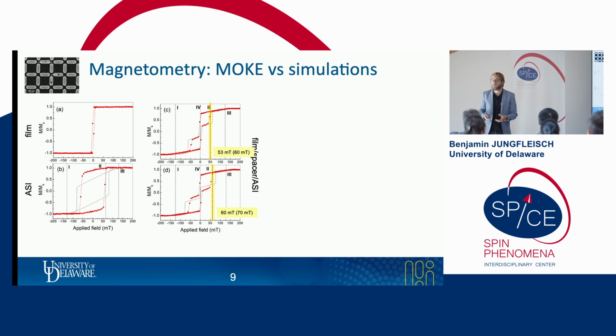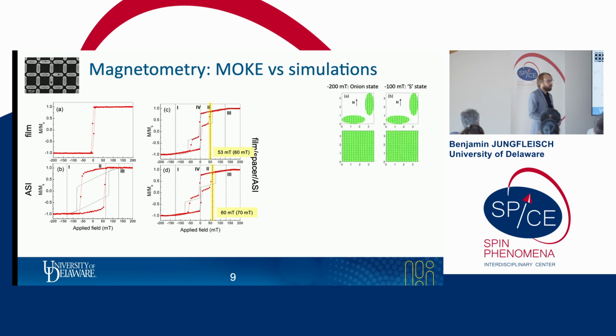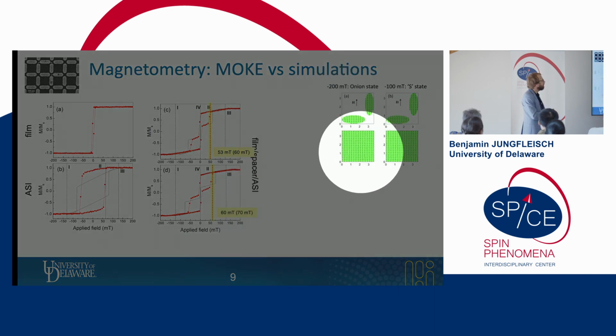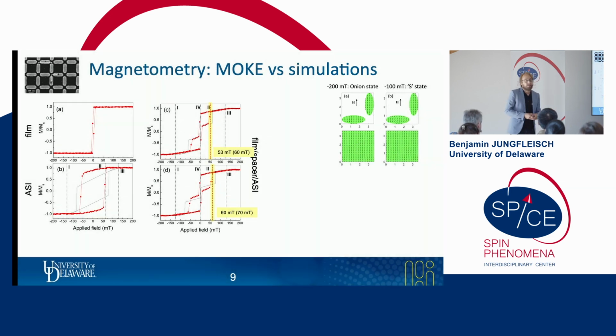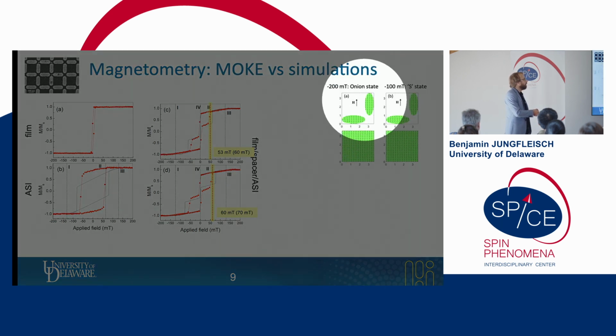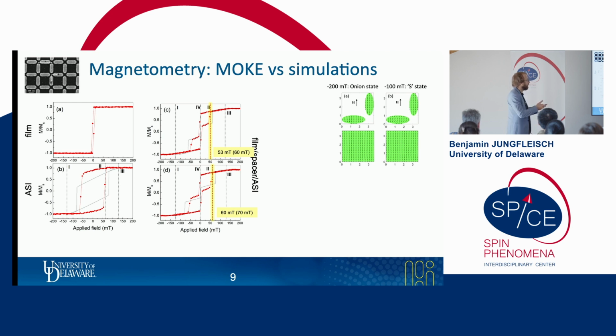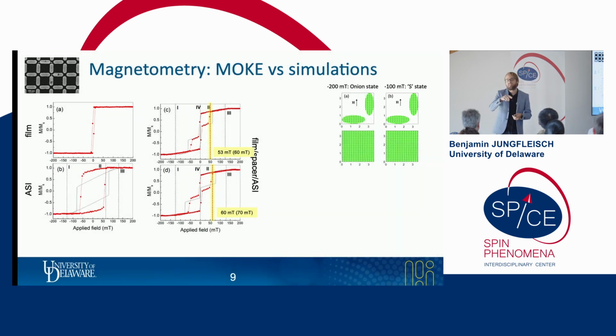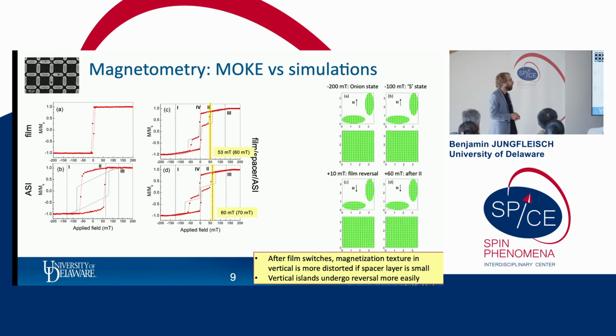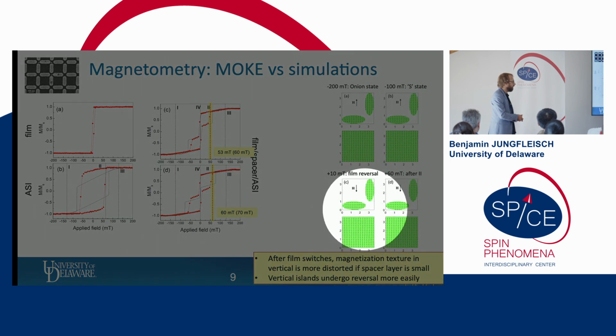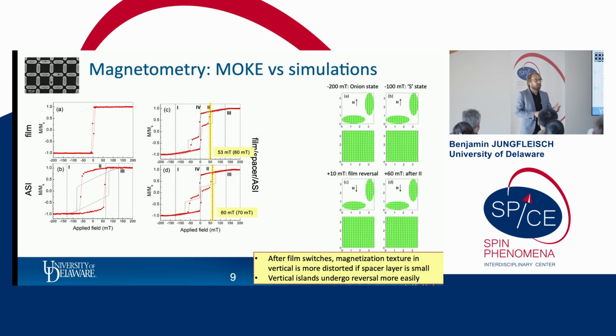Let's take a look at the 2D micromagnetic simulations of the magnetization. On the top, I'm showing the artificial spin ice layer, and on the bottom, the corresponding film underlayer. On the left, we see the result of an applied field of negative 200 millitesla. In this case, the film is completely saturated, and the artificial spin ice shows an onion state. And then if we lower the field magnitude to minus 100 millitesla, we see an S state developing in the artificial spin ice. If we continue to increase the field, at some point the film reverses. This is here the case. And if we continue increasing at 60 millitesla, eventually also the vertical elements switch.